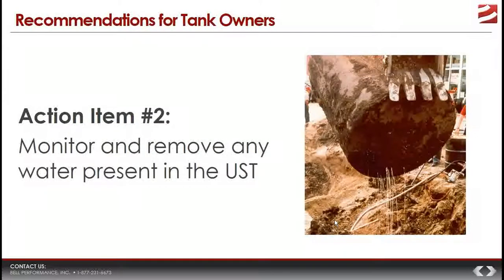So action item number two was tank owners need to regularly monitor for water content and then try to remove any water present that they find. Now, if you've been in the business for any amount of time, you probably already think you know this, and you may well know this, but you would still be surprised at the number of owners and operators of fuel storage tanks across the country who do not actually do this. I mean, up to this point, it should be pretty clear that if you have a water phase in your storage tank, that is going to contribute to a corrosion problem. And not just in how it contributes to microbial growth, but it also does it in something as simple as the oxygen content of the water.